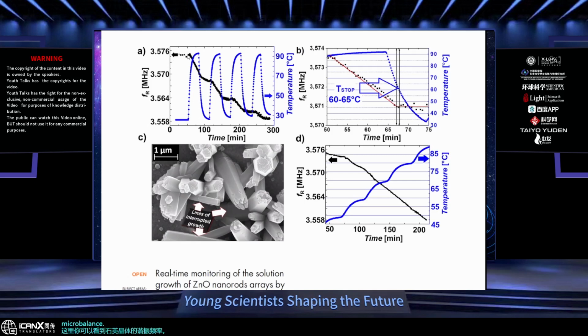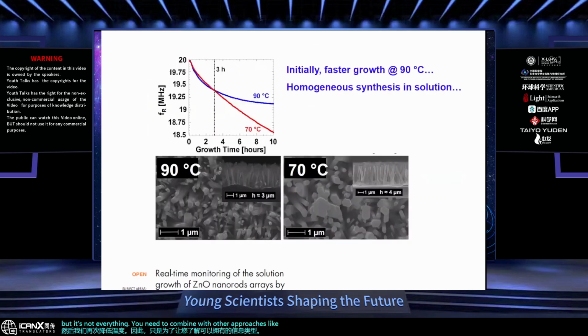So it starts constant. Then when temperature goes up and the nanowires start growing, the resonant frequency starts going down. But then we go down with temperature, and that means that the growth of the nanowires will stop after some time. And therefore, you see that the resonant frequency becomes more stable. Then we increase temperature again. So again, fast growth. And then we reduce temperature again. So just to give you an idea of the type of information that you can have, but it's not everything. You need to combine with other approaches, like we used in combination with SEM images.